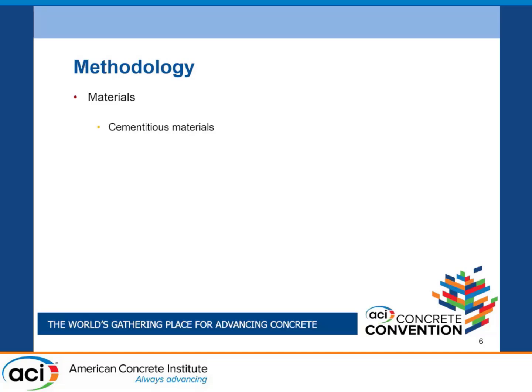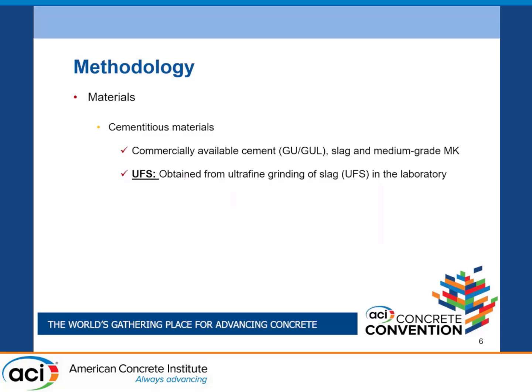The cementitious materials that we used were commercially available cement, a slag, and a medium-grade Metakaolin. The UFS was obtained from ultrafine grinding of slag using a high-energy planetary ball mill in our laboratory. For concrete, we prepared conventional concrete with a slump of 100 millimeters, and dry mix concrete, using locally available aggregates in Alberta. For dry mix, we used aggregates from a concrete block manufacturing plant, and for the conventional mix, we used the aggregates in the lab.